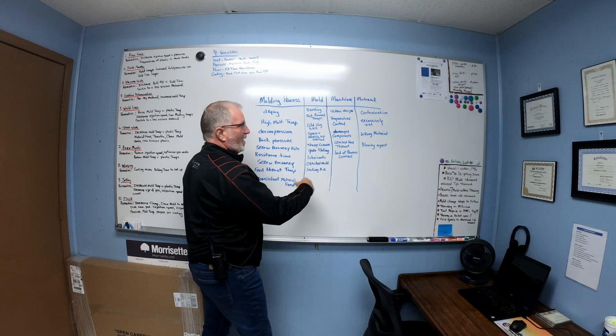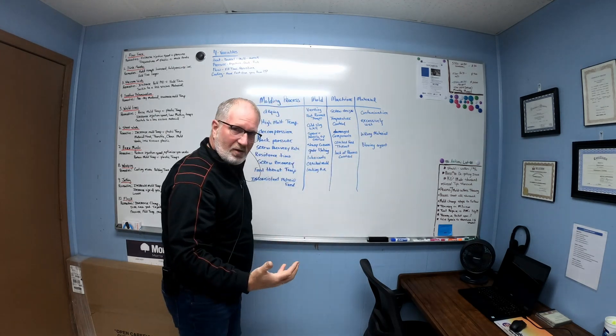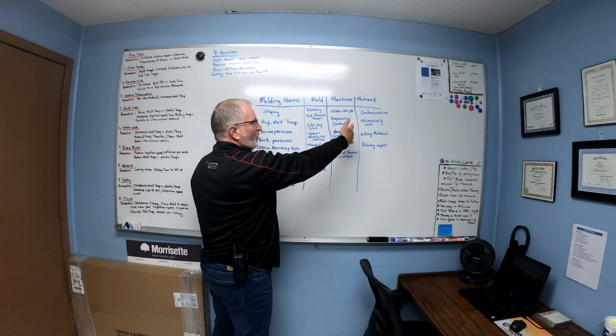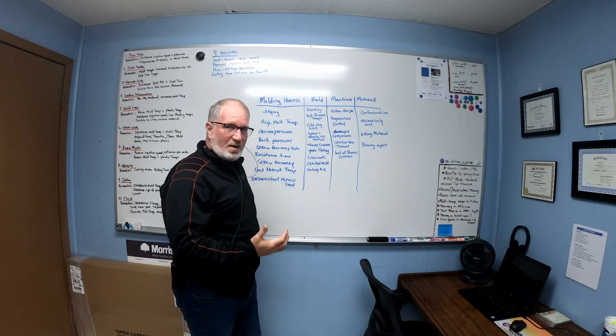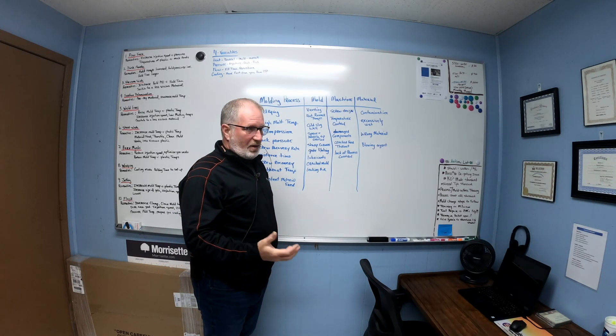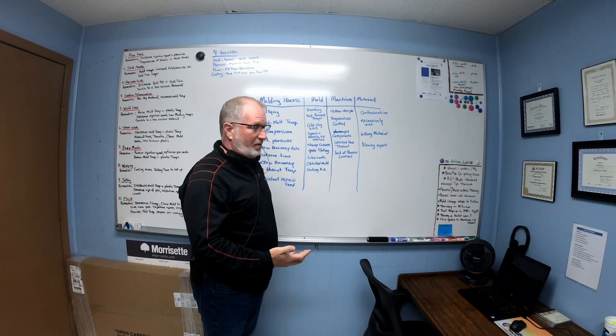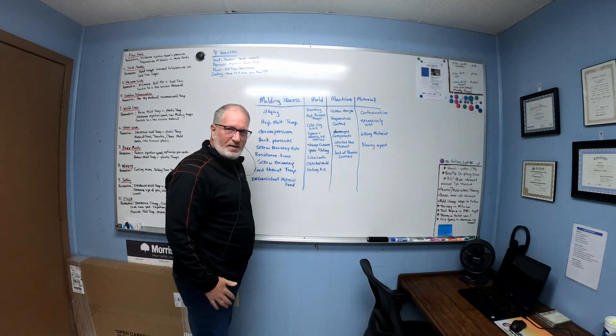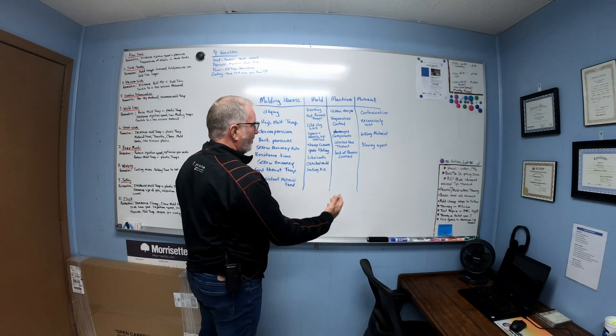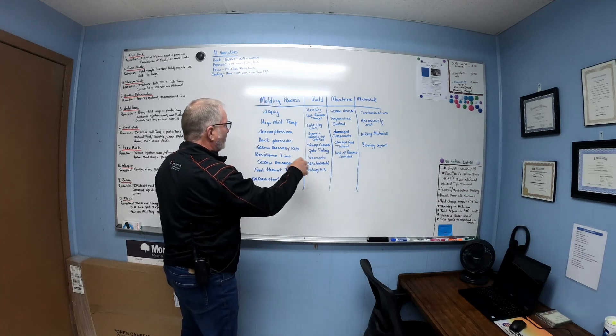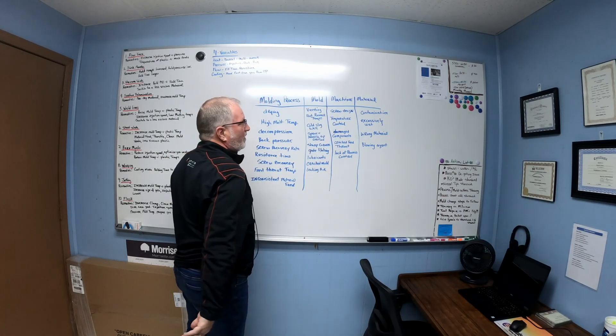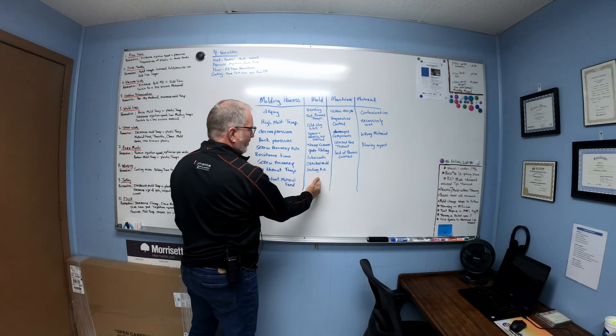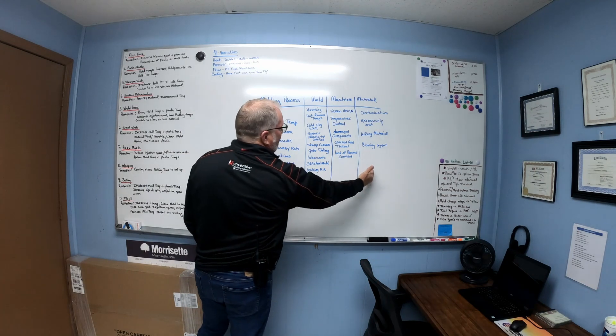Most of the time, a lot of people find this comes down to material. If you've been running a long time and then change to a different material and suddenly see splay, it's likely there. Many people dry their materials — some companies even dry polypropylene. You can also get splay from too much or too little blowing agent. But the majority of the time it usually comes down to a material issue, across all four sides: processing, mold, machine, and material.